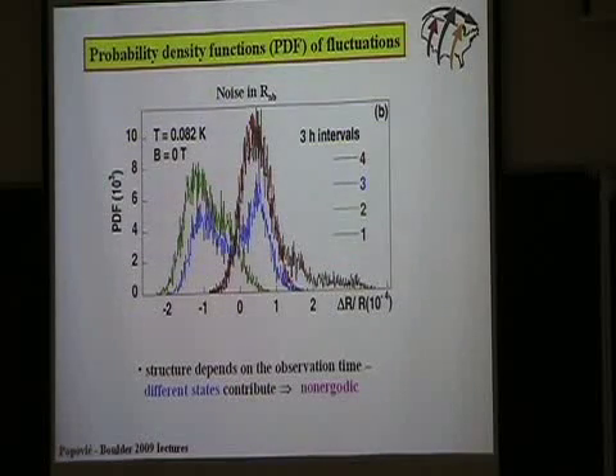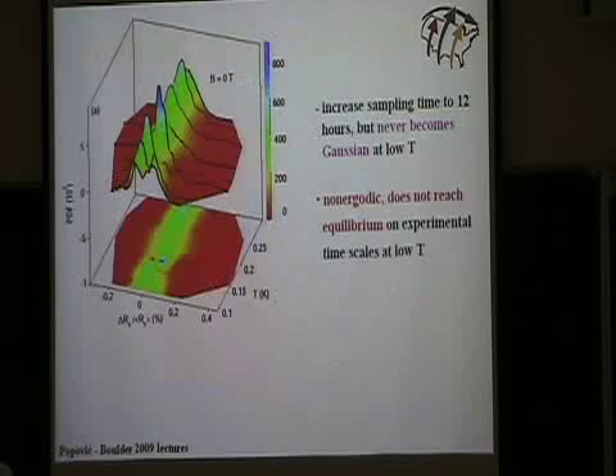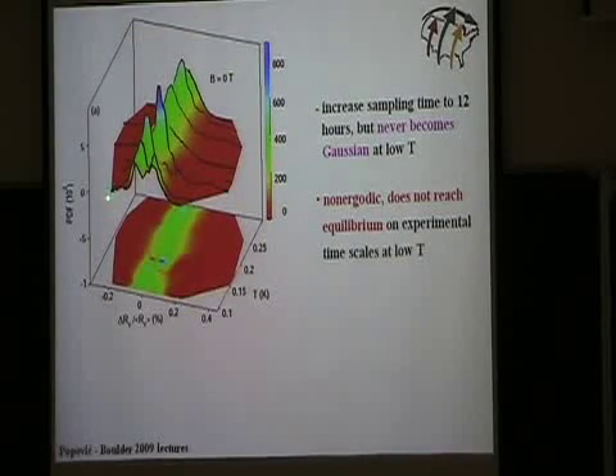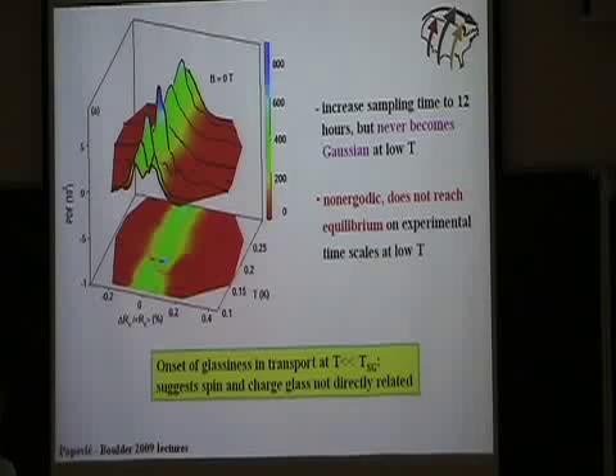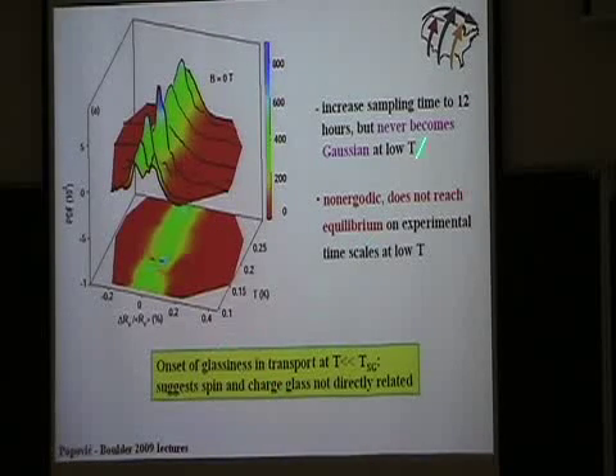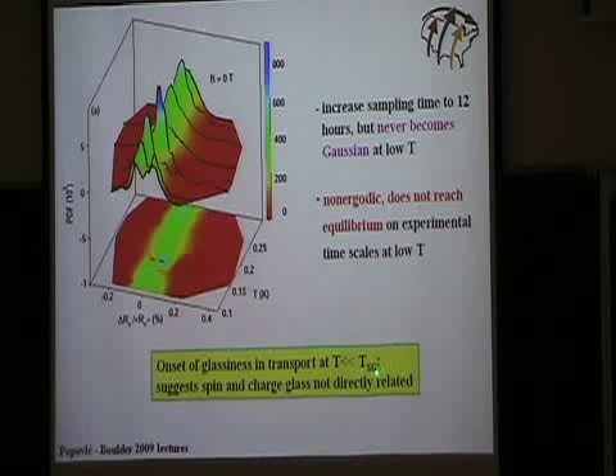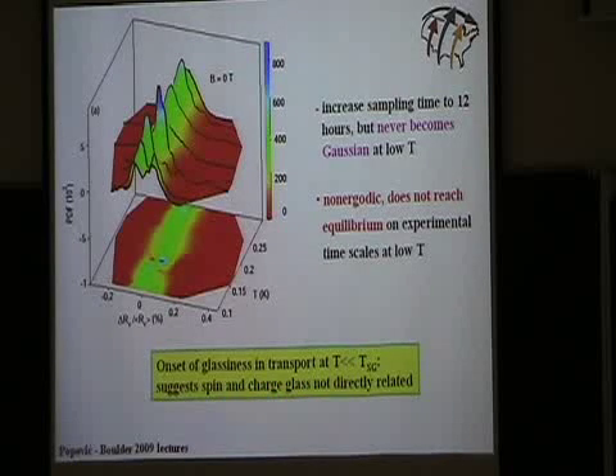So we repeat the same thing again, get the same results. The structure of the PDF depends on the time. We can have 1, 2, 3 peaks. So on the experimental time scales, you cannot reach equilibrium. And these are the PDFs at the lowest temperature for measurement time up to 12 hours. You can see on experimental time scale it's not Gaussian. Only when you raise the temperature, and you cannot see it here, it becomes Gaussian. Okay, so what we find is that this non-Gaussianity in the noise becomes observable at temperatures that are much smaller than the spin glass transition temperature, which is about 7 or 8 Kelvin. And this suggests that the spin and charge glassiness are not directly related.